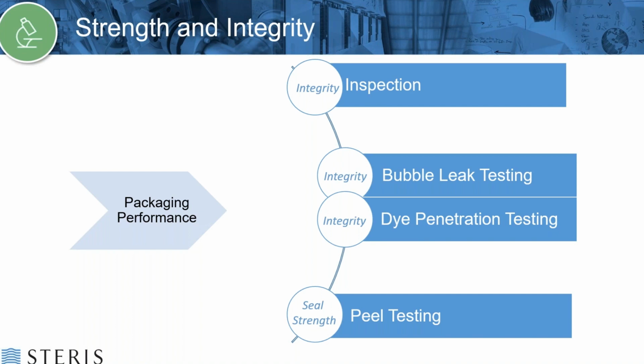The most common seal strength test that we see is a peel test. This is where you're going to cut a segment of each side of the package and pull those two sides of the package apart, measuring the amount of force required to do so.